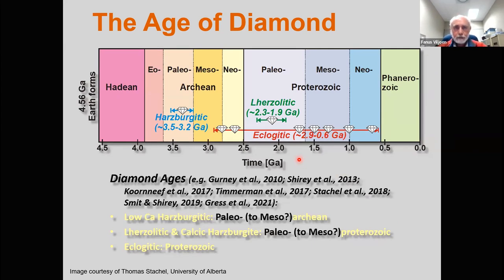So if we date harzburgitic diamonds, and I'm not talking specifically about diamonds that contain purple garnets in them, that have calcium contents less than 2 weight% and have chrome contents that are in the order of 10 to 20 weight% chrome, those diamonds typically come out with an age which is Archean, and essentially ages that are in the order of about 3 billion years or so.